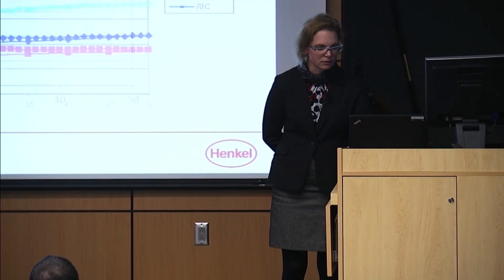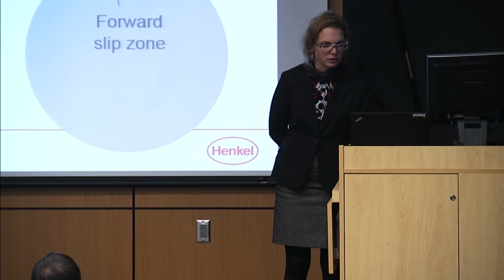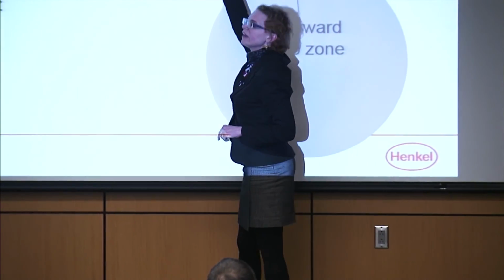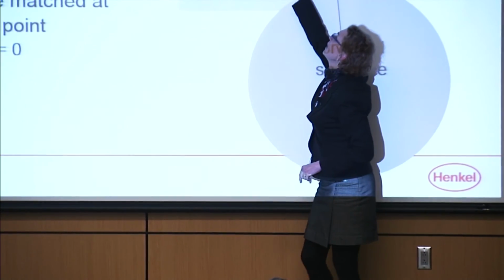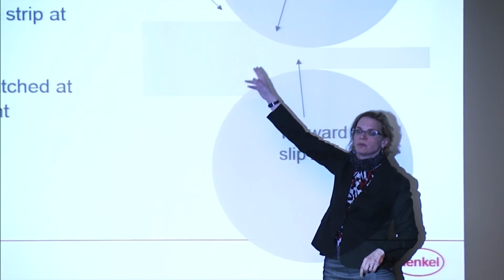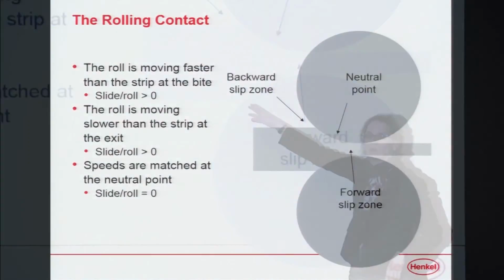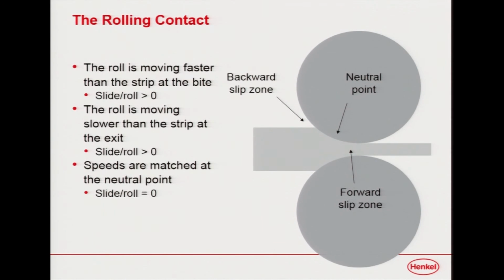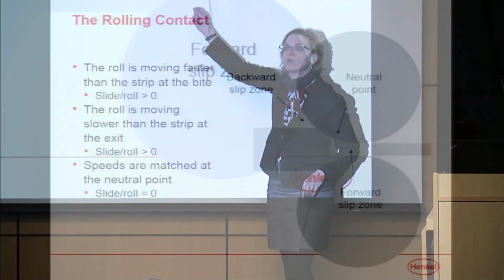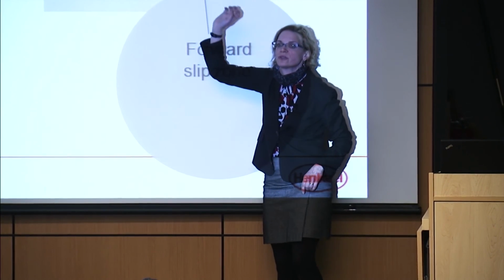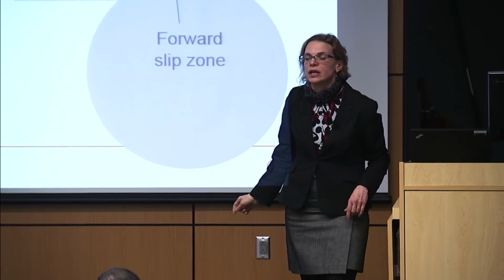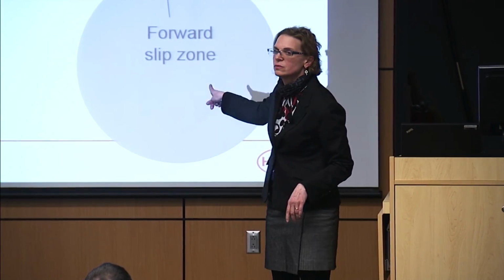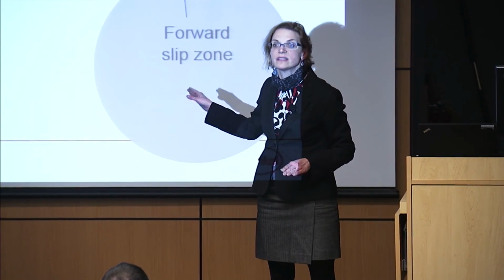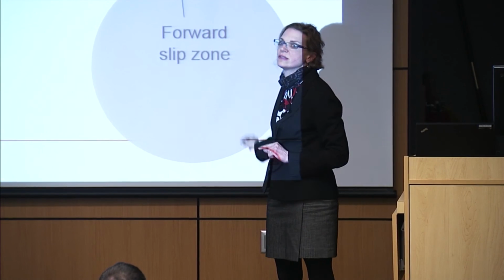What you see is it blows. So let me go back to the model of the mill here. What you would typically see is a lot of evolution of gas on this side, but by the time you're a couple of degrees into the contact, you're well past the compression point of steam. So you will have a full liquid in the interface all the way out to a few degrees before you exit the contact, and then again you will start to form a gaseous layer. And the advantage of that is it actually blows the strip off the work roll. So especially in cases where we're using a water-based lubricant, we are absolutely looking for that. And it's typically steam. We don't want the other molecules to gas. We want just steam gassing here.